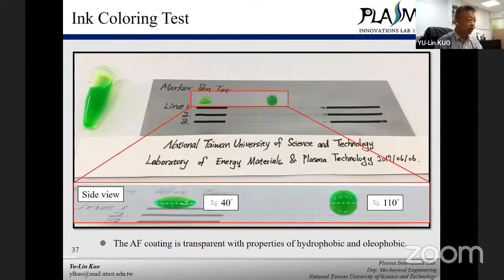And we also use the oil-based pen to draw the line. You can see this region is quite clear compared with the untreated areas. So, which means that with the plasma system, the coating can be done with hydrophobic and oleophobic properties on the surface.